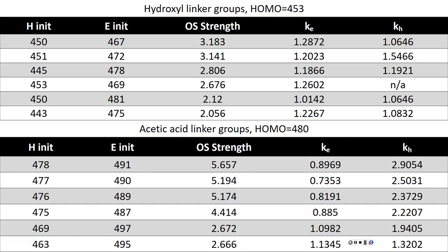They may both reside on titanium dioxide, another neutral, which is probably not the case because you're not expecting excitation on the titanium dioxide quantum dot, right? But you can check it for sure. It's better to check. And there are two other possibilities. When the electron is on perovskite, the hole is on titanium dioxide, and the opposite: the hole is on perovskite and the electron on titanium dioxide.